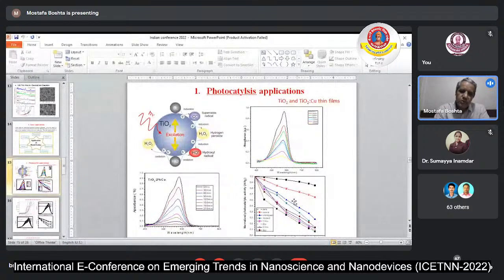And we conclude all this efficiency in this graph. As you can see, when we add the copper to the titanium dioxide, the efficiency and the performance of the material can be increased and improved, and we can get a lot of decaying of the dye inside the material, because dye, as everybody knows, is a pollutant chemical output of some industry, like textile or some chemicals company. So we need to clean the area from these dyes, so we can use this material, titanium dioxide, in the